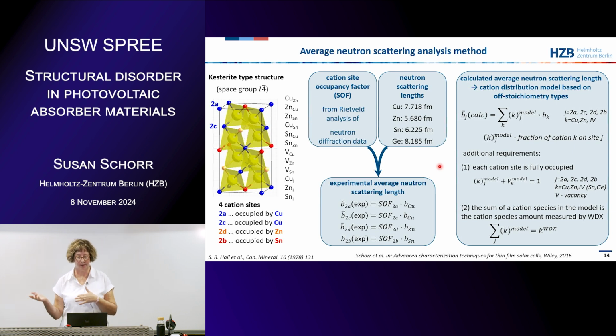Then we have to compare this somehow with the cation distribution we have on these 4 sites. So what we make is a cation distribution model. So we distribute our 4 cations on the 4 different sites, and from that we calculate an average neutron scattering length. So we take the assumed fraction of a cation on the Wyckoff position J, and then we have to multiply this, of course, with the neutron scattering length of the cation, and then we get this calculated average neutron scattering length, which we then compare with the experimental one. And then we change the cation distribution model until we reach agreement as good as possible between the calculated average neutron scattering length and the experimental neutron scattering length.